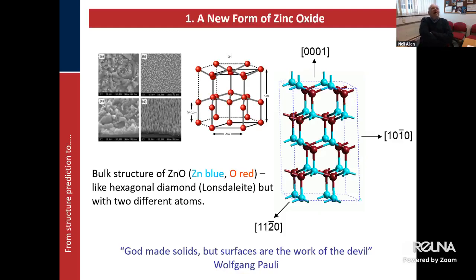And then actually it made sense. Thought about it a little more, and it made sense, because physically what was happening is that the layers coming together removed this dipole, because now each layer had an equal number of cations and anions. And actually, it wasn't that unusual anyway, if you think of the chemistry of carbon. Now, if I was to take that Wurtzite structure and replace all the ions with just carbon, I would be actually forming one of the forms of diamond.